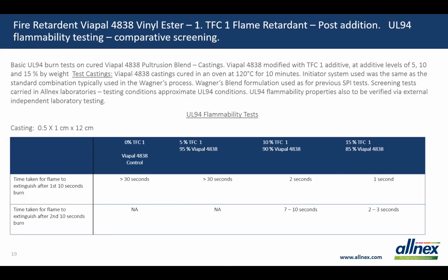Okay, so as far as the UL94 flammability, some results here. We found from our initial UL94 fire testing evaluations within Allnex, and we don't have fully controlled conditions on our rig, that approximate UL94 V0 results can be achieved at levels of this additive between 10 and 15%, with around about 12% being, we believe, the sweet spot. It was quite positive. The effect on fire retardancy was quite definite.